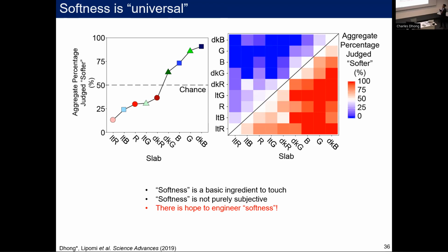And what that's saying about my data is that if I gave someone sample A, and they found A to be softer than B, and then they found another sample, B was softer than C, then A has to be softer than C. And this is happening across 9 samples across 10, 15 subjects. So the idea is the order of softness between subjects and in between themselves is consistent. So this is called transitivity, right? A softer than B, B softer than C, A softer than C. That means that everyone has a similar concept of softness from the people we tested.